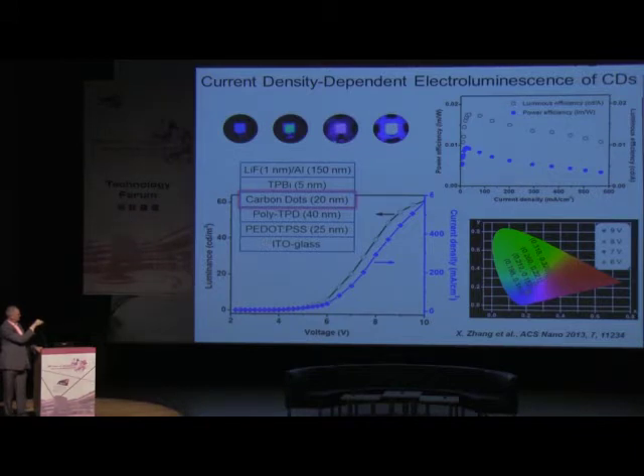So this is a structure of LEDs. There is a hole injection layer, electron injection layer, a light emitting layer in between, which is based on carbon dots. The so-called turn-on voltage of these devices, that's the voltage which we apply and they start to emit visible light, is 6 volt. And we have seen that the color here depends very much on the